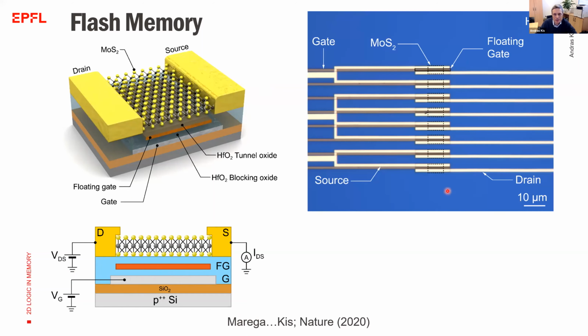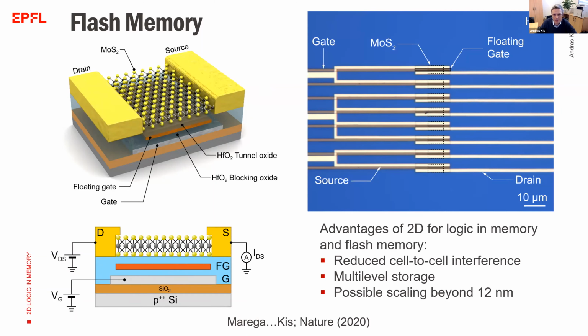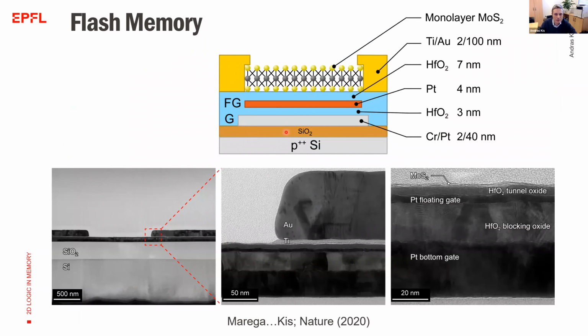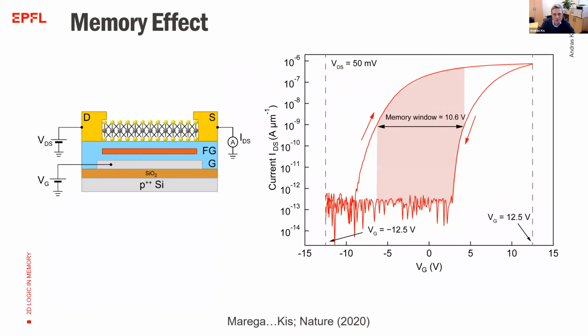So because we can make these semiconductors on a wafer scale, we can in principle make relatively complicated structures. So this is an example of a small circuit with 8 of these transistor elements. And if you look at the cross section of the devices, we can see that we can very nicely and very reliably, due to this process where we have first everything done on the wafer scale and then we transfer the 2D semiconductor on top, make a lot of these elements in parallel.